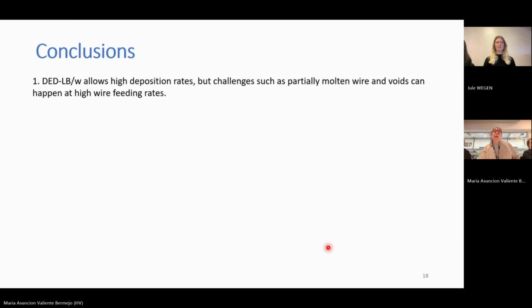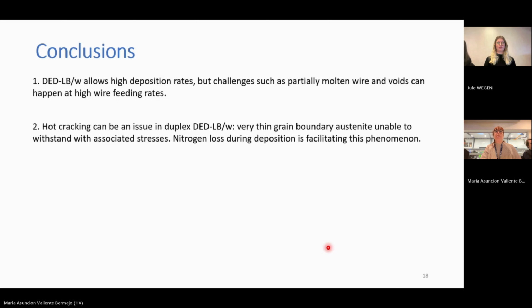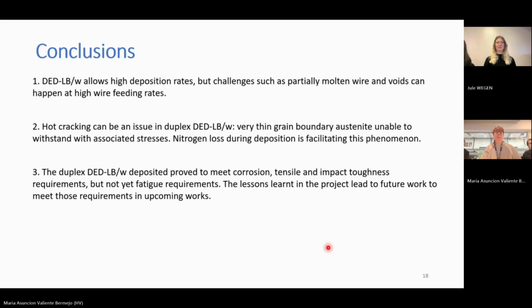Then the conclusion from our side is that the process, this DED laser beam wire, allows high deposition rates, but there are challenges such as this partially molten wire, the voids or pores that happen at high wire feed speeds. Hot cracks are normally not a problem in conventional welding for duplex, but we have seen this as a problem here. This very thin austenite and also the possibility that nitrogen is lost during the deposition are facilitating this phenomenon.